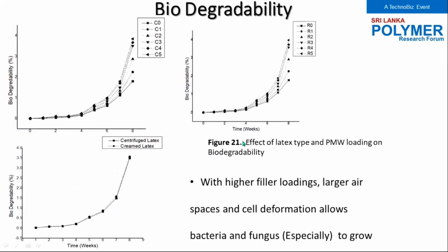The biodegradability is the main point that makes our natural rubber latex foams more eco-friendly. So for biodegradability, I have measured it over time from 0 to 8 weeks. For the 8 week time period, you can clearly see it has increased. It has increased in both types of latex, and also the addition of mica is a kind of support for being biodegradable. With higher filler loading, larger air spaces and cell deformation allow bacteria and fungus to grow there, and also the bacteria-rich medium could improve that parameter.